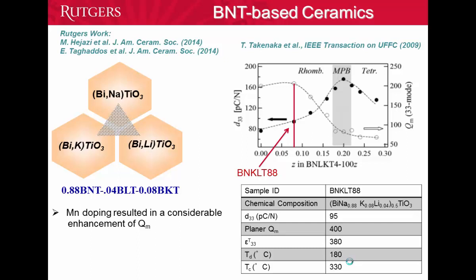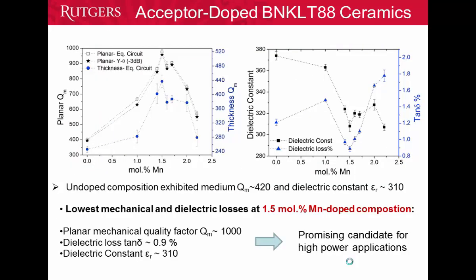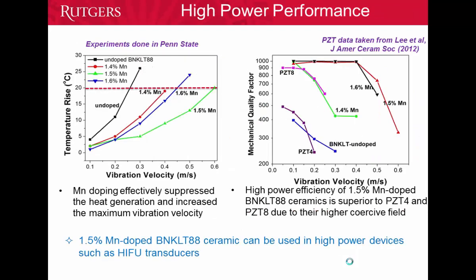And then we have been trying to enhance the electromechanical properties of these compositions by manganese doping as an acceptor dopant. Here you can see that the mechanical quality factor incredibly increased by doping manganese. At the level of 1.5% manganese doping, the mechanical quality factor in both planar mode and thickness mode reached the highest value. And at the same amount of manganese doping, we could reach the minimum dielectric constant, which is favorable for high power applications. So it motivated me to measure the high power performance of these compositions under high drive conditions.